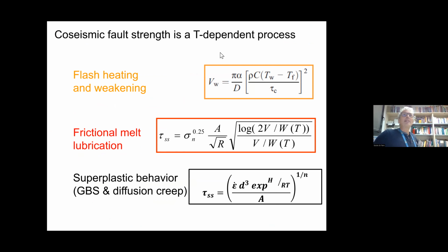But I want to summarize some constitutive laws. They're very complicated to use in numerical models. This could be for flash heating and weakening. There is some dependence of the critical velocity, but from this you also get the frictional values, how the friction evolves with the velocity. Then you can have this complicated one, which relates shear stress with slip rate, and there is a normal stress in between. Or another one, which is a superplastic behavior, the one we discussed about calcite gouges.